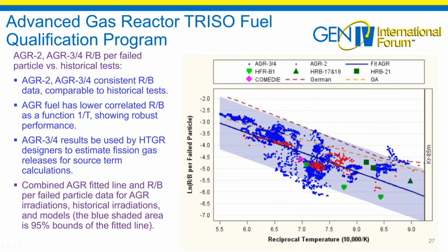Now let's look at this. Did we get results that make sense here? This plot shows the log of the release to birth ratio, basically a measure with the krypton-85, against the reciprocal of the temperature. So as the temperature goes up, you're going to basically go in the opposite direction. So we have krypton-85 measurements, and you'll see that we have some of the historic tests, the German